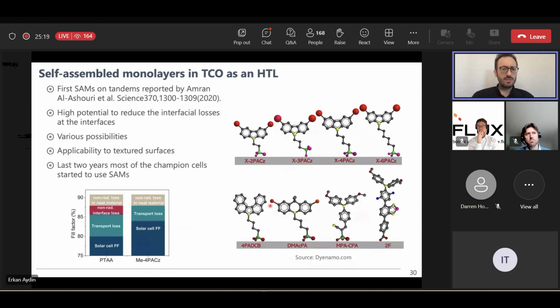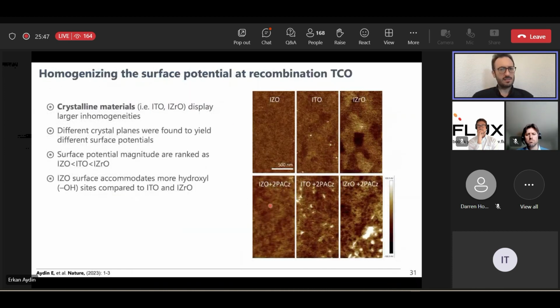But later on in 2020, actually, the team of HZB and Kaunas introduced the self-assembled monolayers on tandem cells. Indeed, it was an interesting thing for us as well because we were able to form a conformal coverage on the textured interfaces. Basically, it's a self-limiting reaction, and in the end, what we got out of the cells was quite good.